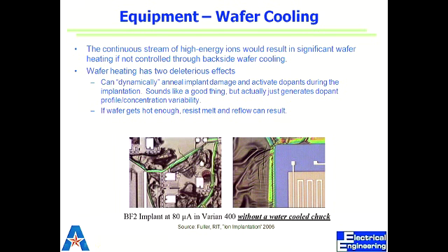During implantation, that heating up can result in activating dopant and healing the substrate, but we don't want that at this stage. What we need is for the dopants to go to the depth that we want. We don't want them to be activated because that's going to change the concentration profile, and then the resist reflow can cause the region that we want to be doped to change.